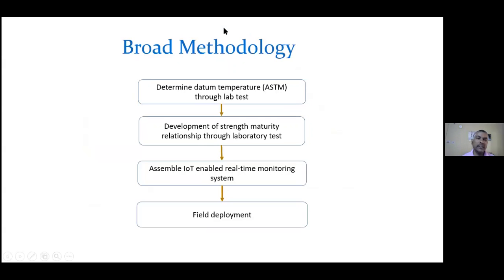So the broad methodology is, first, for a given mix of concrete, we calibrate this maturity method. What does that mean? That means we find out the datum temperature and also the constants that we have to find out for calibration. Once we know the constants and the datum temperature, we know the strength maturity relationship. That we do at the laboratory. Now this strength maturity relationship is completely known to us.